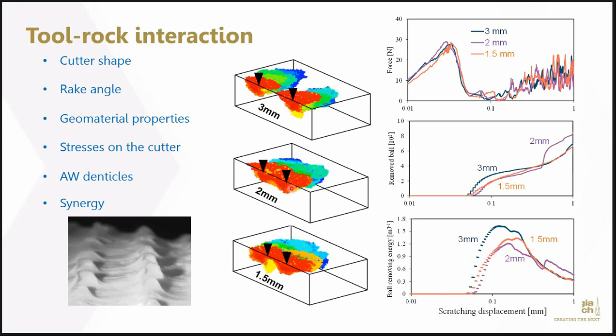There's a synergy, or there's an optimum distance between the two denticles if they are scratching simultaneously. That can give you a better performance. So the relative distance between the two cutters is also very important. You do not want to overcrush the materials in between. You also do not want the two separated too far away, so that each of the denticles will act independently. So you do want to control an optimum distance that can give you the maximized cutting efficiency. So that's what we see here in the results, as well as in the actual angelwing denticles.